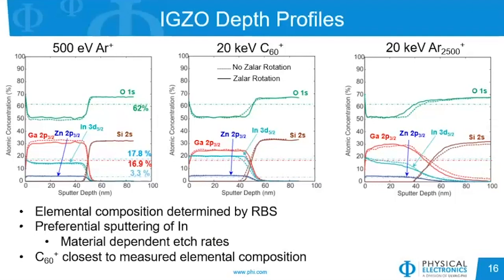We also look at the gallium concentration for C60, which is closer to the 16.9 expected value compared to that of the monoatomic argon. Looking at the argon gas cluster, we can see that in general we really don't even get a uniform concentration through the material, as it seems to always be decreasing or changing. And so from this example, it looks like the C60 has given us the closest measurement relative to that of RBS for the intact material.